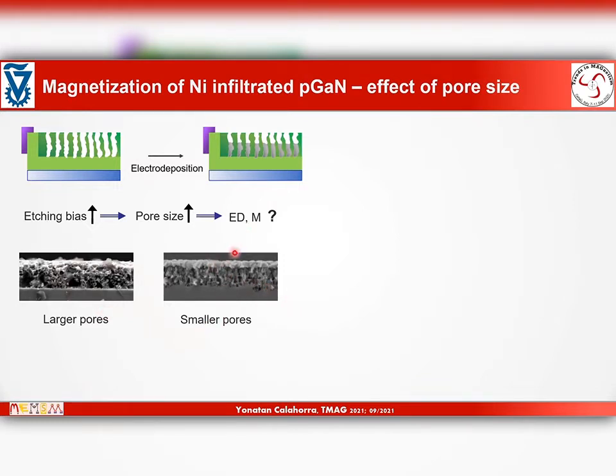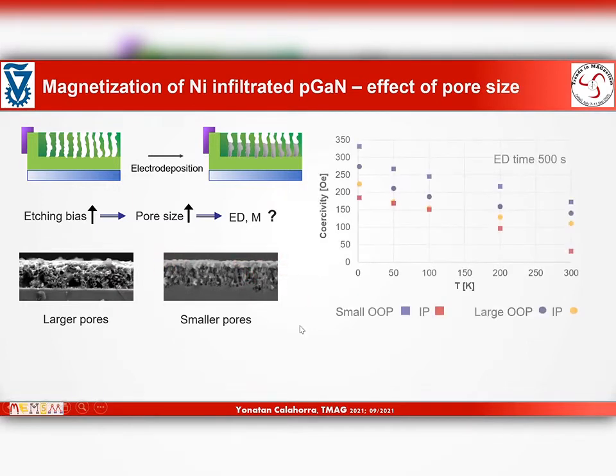We can see that the electrodeposition on top of the smaller pores resulted in a layer, while in the larger pores it resulted in less of a layer and more embedded nickel. This is not a direct result of the pore size, but also some coupling between the pore size and the conductivity of the sample: the smaller pores were more conductive, and hence the electrodeposition took place on top. So what about the magnetization? We carried out a series of VSM measurements, and we can see that in the small pores, when we look at the in-plane and out-of-plane coercivity, there's a large difference in squareness between what we get when we have an easy axis, which is in-plane with lower coercivity, and a hard axis, which is out of plane.